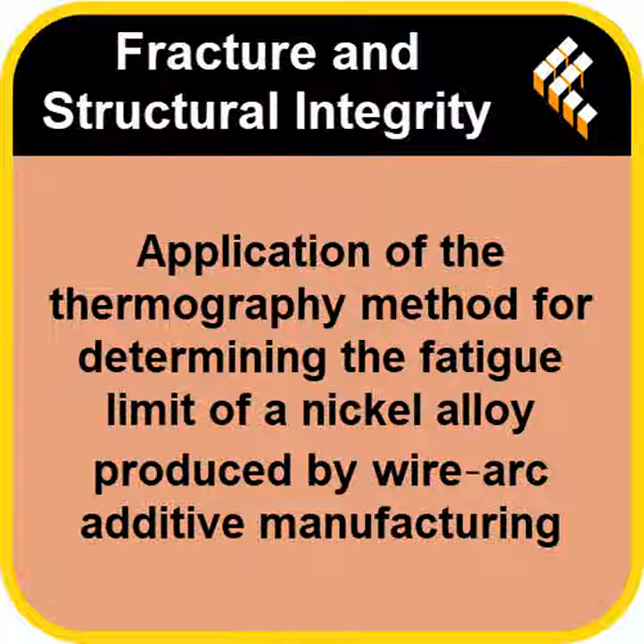By using the rate of temperature rise, they only needed between 6,000 and 12,000 cycles for each block. That's what cuts the test time down from months to hours. You get the critical piece of information, when the damage mechanism turns on, without the huge time sink.